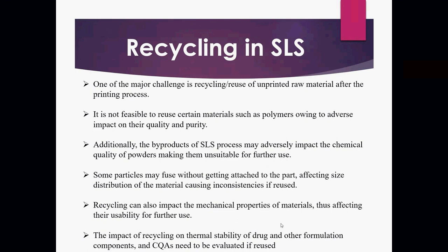formulation characteristics. Sometimes some particles will get fused from the laser, but will not get attached to each other. Then the particle size distribution will be different. It will affect the mechanical properties of the material. It will have a complete impact on the quality attributes of the powder.